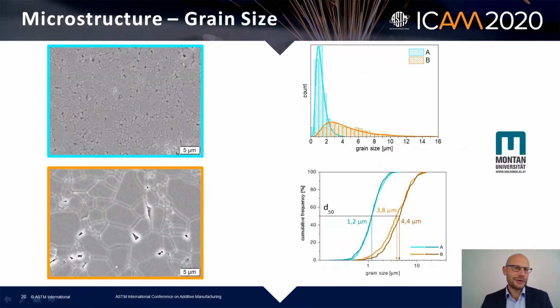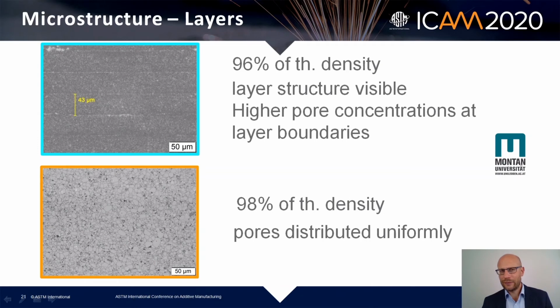First of all we took a look at the microstructure and the grain size. What is of course very clear is that the grain sizes are different because the sintering temperature was different. We would have expected, and this is what we see here, that the lower sintered ceramics have a much finer grain size and a much more even pore size distribution, whereas the materials sintered at higher temperature have a broader spectrum and much coarser grains. But there's also a different density, of course. So we achieved 96% density and 98% density respectively.